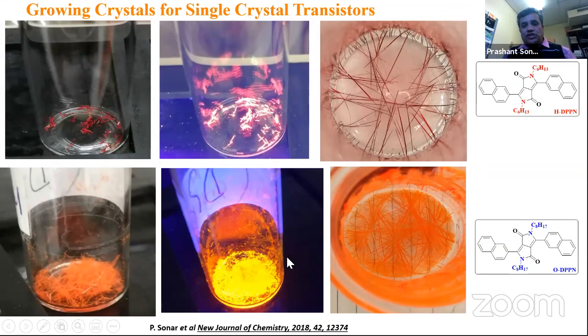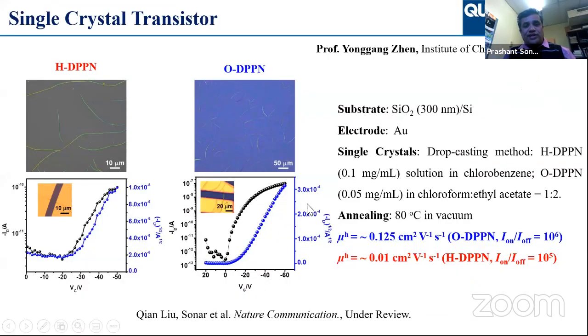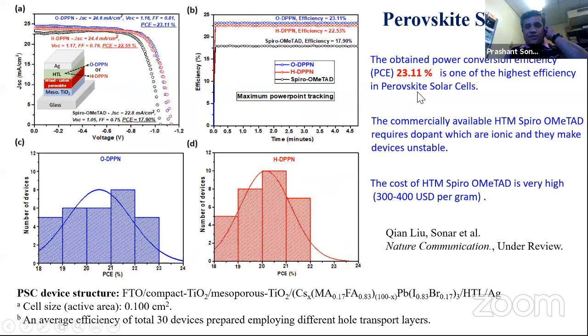And those crystalline materials can show very high hole mobility, up to 0.125 in a transistor. We also tested them in a perovskite solar cell, and we could reach efficiency in a very high regime of 23%. But again, these are one-time data. I'm chasing Sagar to get much more thorough data, and we may also need to certify these numbers to really get reproducibility.